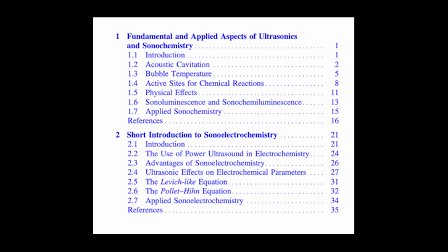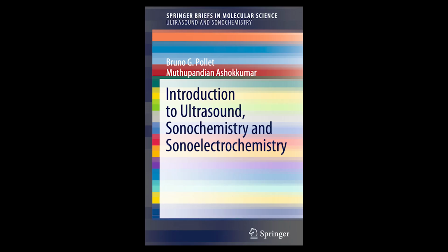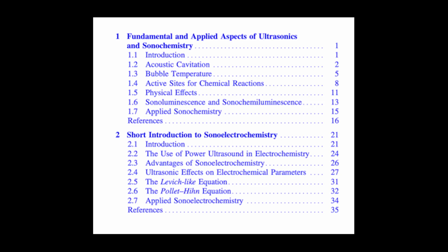Okay, so we can see the effects clearly. Now, how do we move towards engineering control? We need models, equations that relate the cause, ultrasound power, to the effect, electrochemical current. How is mass transport quantified in SEC? This is crucial for designing reactors and comparing results. For standardized setups, especially what's called the face-on geometry, where you have an ultrasonic horn pointing directly at a flat electrode surface, researchers developed relationships analogous to hydrodynamic equations.